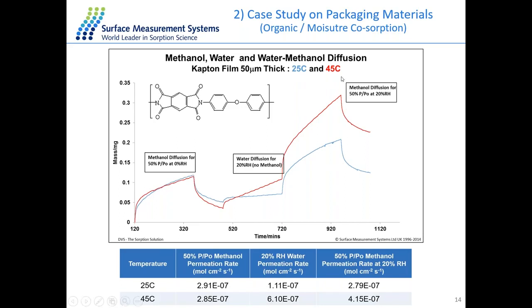However, for the last stage, which has the presence of both water and methanol, the permeation rate at 45 degrees is a little bit larger than at 25 degrees. And there is a huge difference in the plot as well. That means the background humidity helps the methanol molecule get a faster diffusion at higher temperature as well. So this study shows you the potential to measure the influence of temperature as well as the influence of background humidity for the membrane sample with the DVS technique as well as the pen cell application.